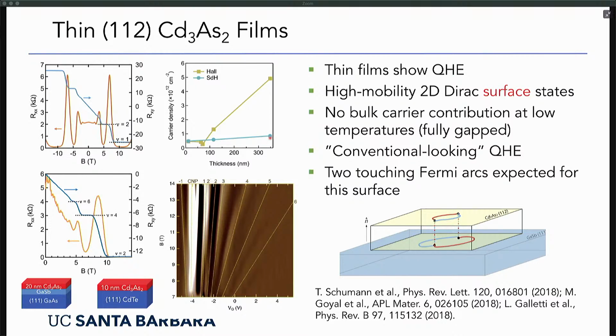I don't show all the studies, but here, for example, if you look at this as a function of thickness and compare the Hall carrier densities with the carrier densities from the quantum oscillations, you see the Hall carrier densities for thick films are fairly large. We make the films thinner, the films gap out, we lose the bulk carriers, and the only remaining carriers are those in the surface states. Those are the ones that give rise to the Shubnikov-de Haas oscillations. For thin films, the two carrier densities agree, which means all the carriers are in the surface states. So that's one way of showing that these two-dimensional carriers are really in the surface states.